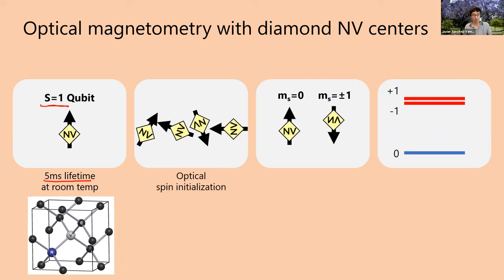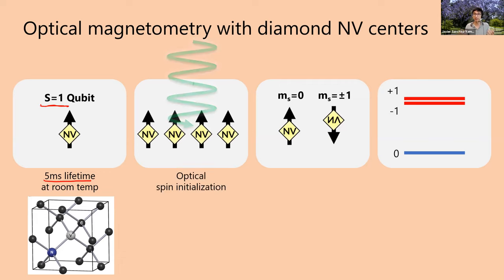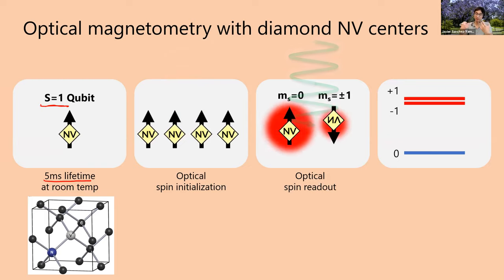The second thing, which is pretty remarkable and beautiful, is that if you shine green light onto the NV center, it polarizes. You don't have to cool it down in some dilution fridge, as people do with semiconductor spin qubits. You just shine light on it and it'll polarize into a spin state with high fidelity. For similar microscopic reasons, you can also read out the spin state optically. If you shine green light on it, the NV center will fluoresce red, and if it's in the ms equals zero state, it'll fluoresce more brightly than if it's in the ms equals plus or minus one state. So you can distinguish whether you're in the zero or the plus-minus one state.